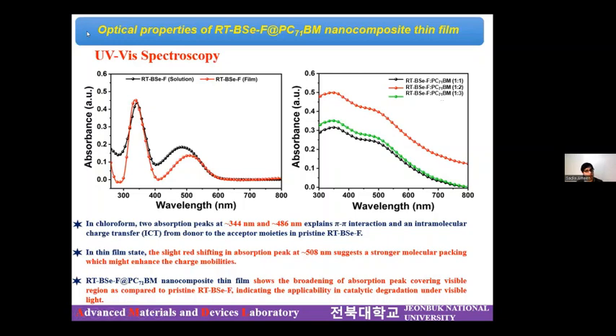Then we performed certain optical properties. As you could see from the UV spectroscopy, this is the UV spectroscopy of the synthesized organic molecule, and we did it for the solution as well as for the thin film. In the case of the solution, we obtained two significant peaks, which might correspond to the pi-pi interactions. And when we made the thin film of this small organic molecule, we noticed a prominent shifting, that is the red shifting, which suggests molecular packing, which might